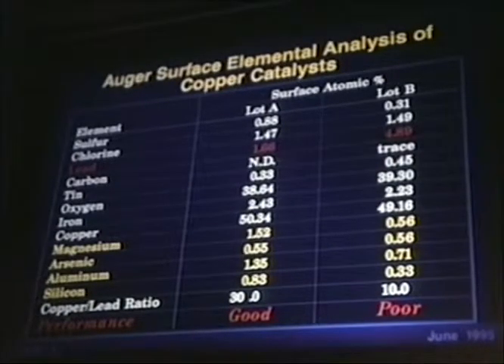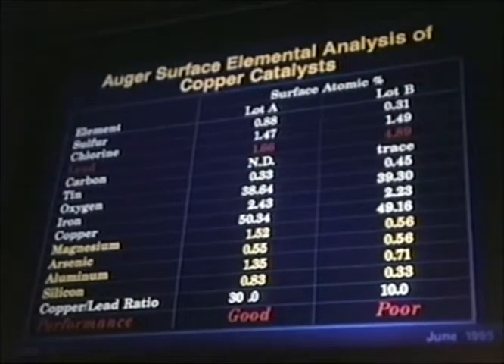The concentration of lead on the top surface layer may even be several fold higher if all of the lead is enriched on the top layer. As you know, Auger goes several layers deep into the surface. The good activity catalyst, hence, was not only low in lead, but also had larger amounts of the promoters. The larger amount of lead in the poor sample on a further diagnosis is believed to have resulted from the migration of lead to the grain boundaries of particles during a catalyst roasting step. These findings were later confirmed by ion scattering spectroscopy, which is very sensitive to the surface analysis.